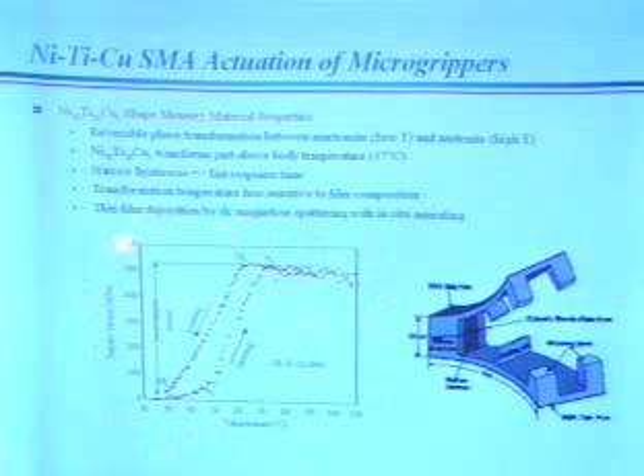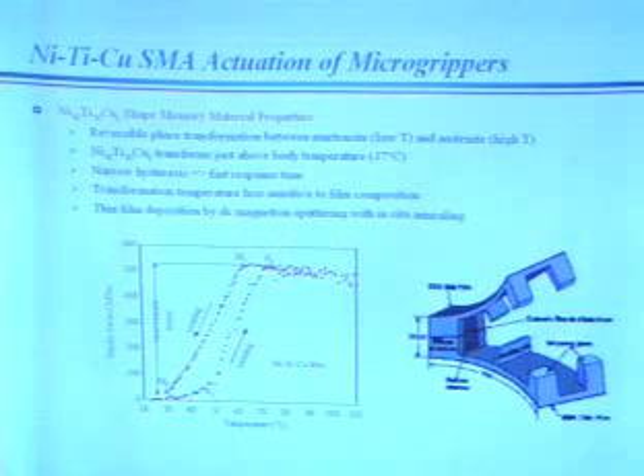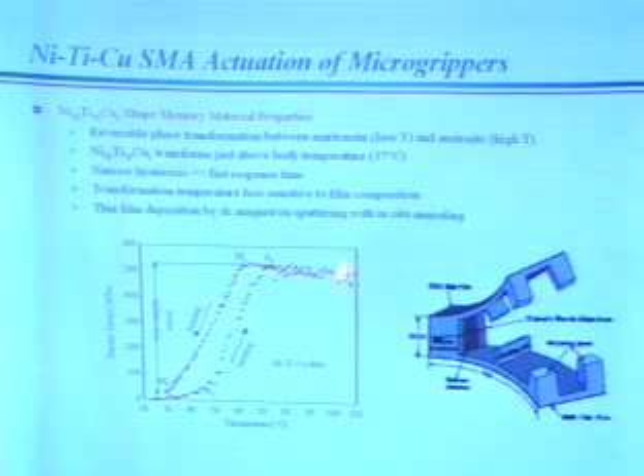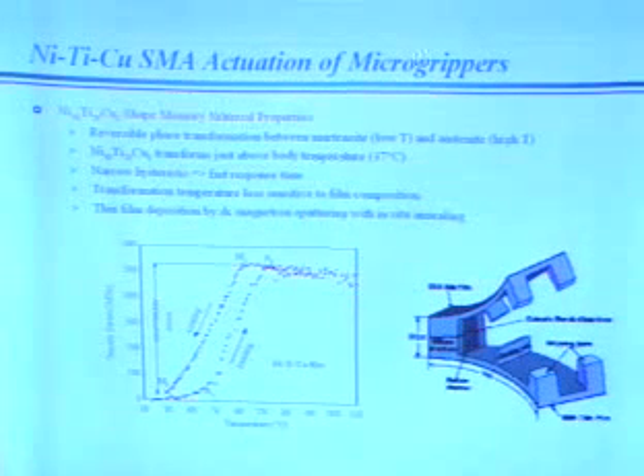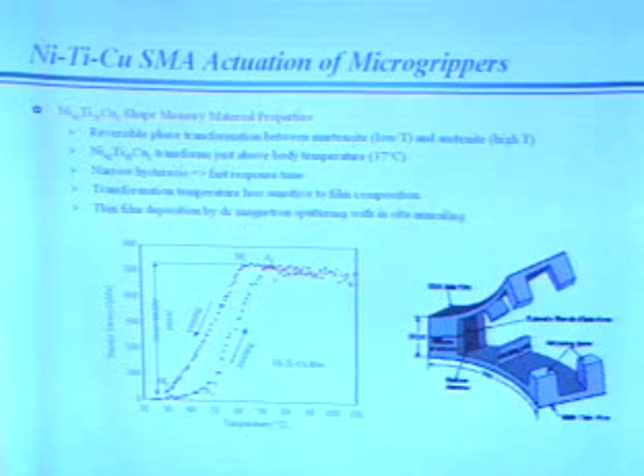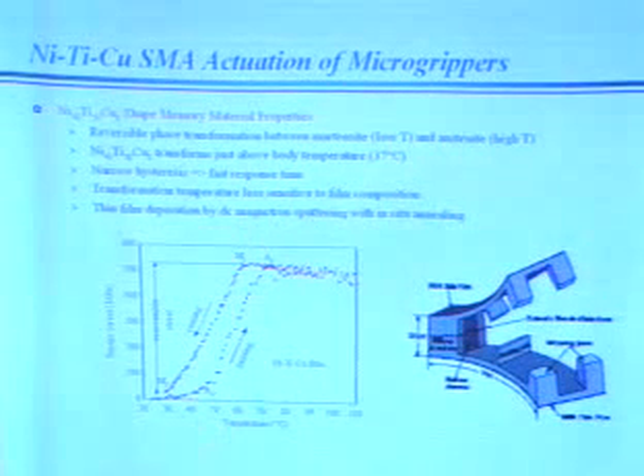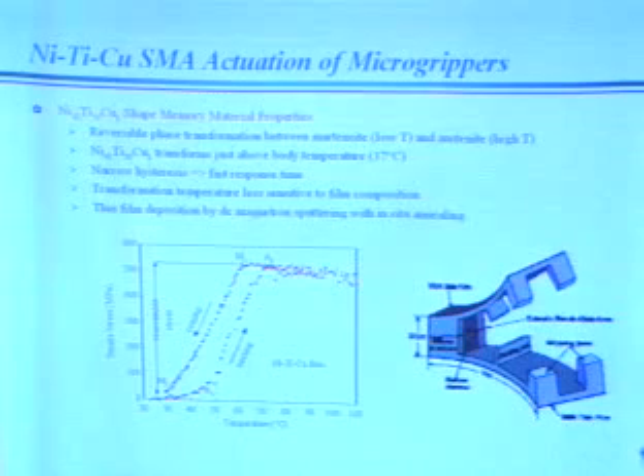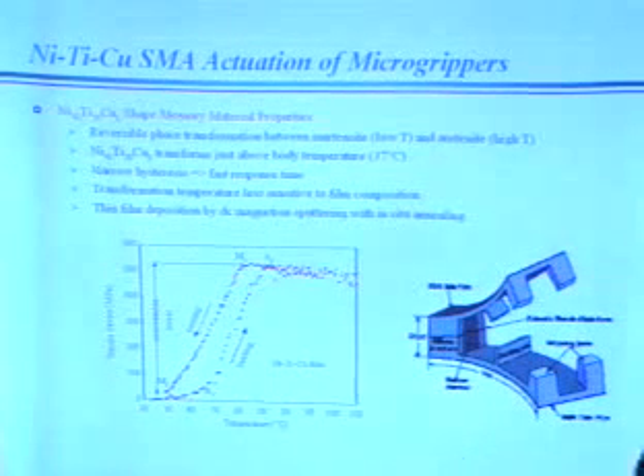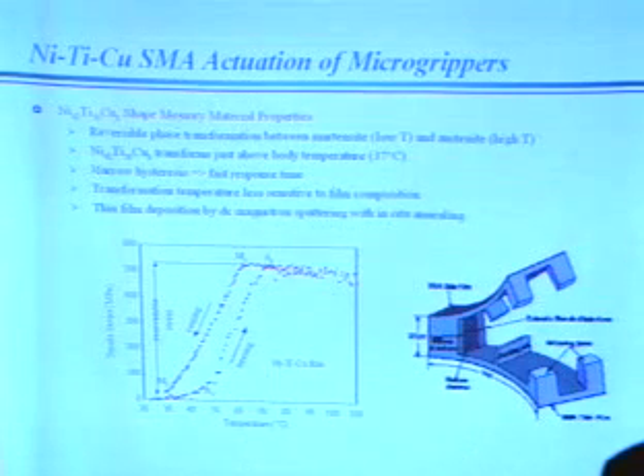This is a lot of explanation to do, but I worked with my colleague Peter Krulovich, and he was the material scientist who developed the magnetron sputtering technique for this nickel titanium copper. To make a long story short, the copper addition allows you to really focus in on a certain transformation temperature range, and also gives you relatively narrow hysteresis, so you have relatively fast response times. The other critical point is you still maintain the high stresses that you have with nickel titanium. The copper addition is actually more for manufacturability, because without copper, nickel titanium shifts by a few percent, and you shift the transformation temperature by tens of degrees. So it's hard to really control that.